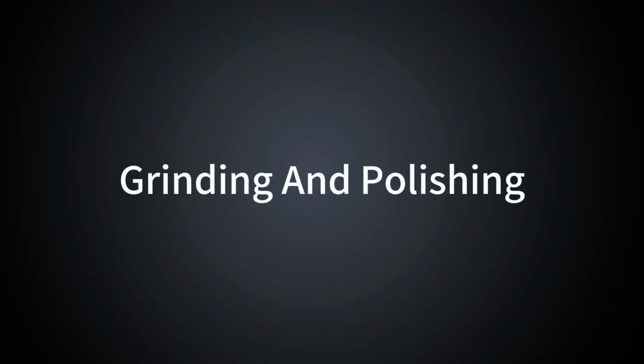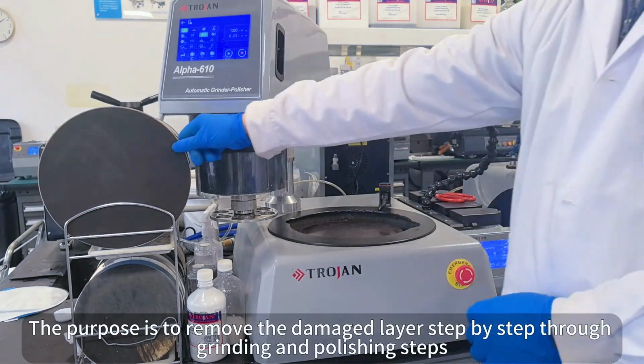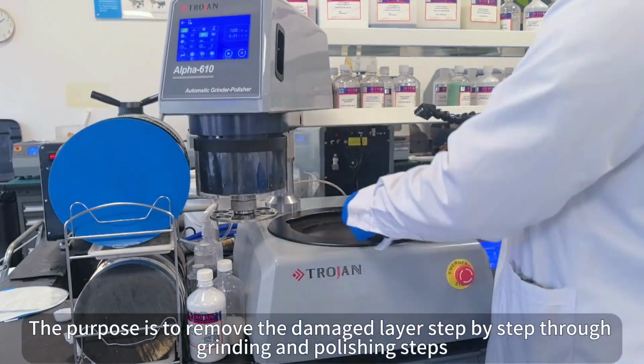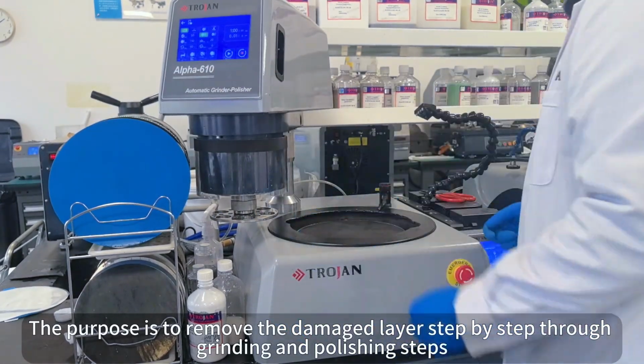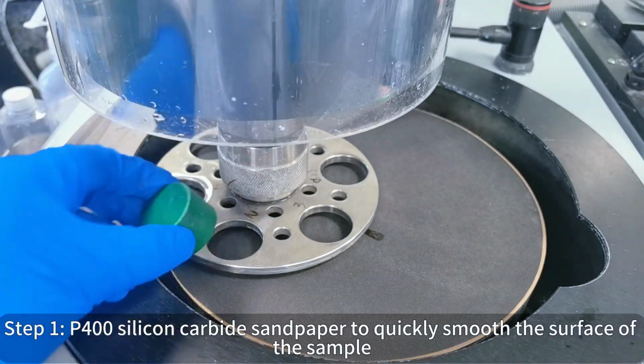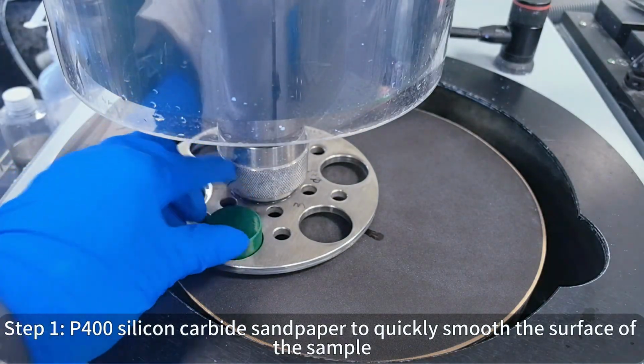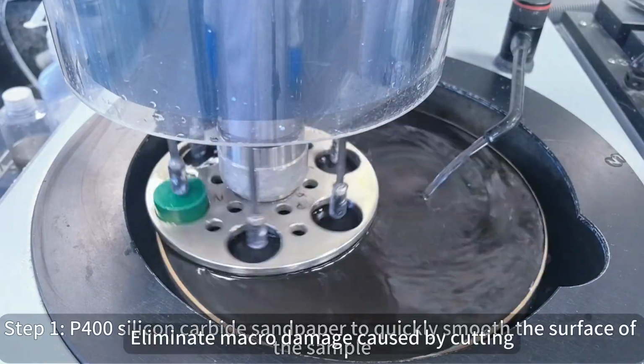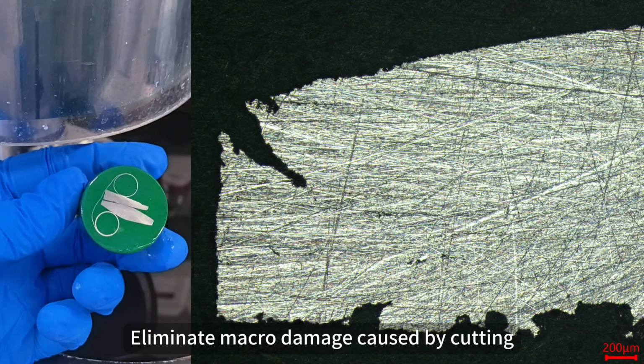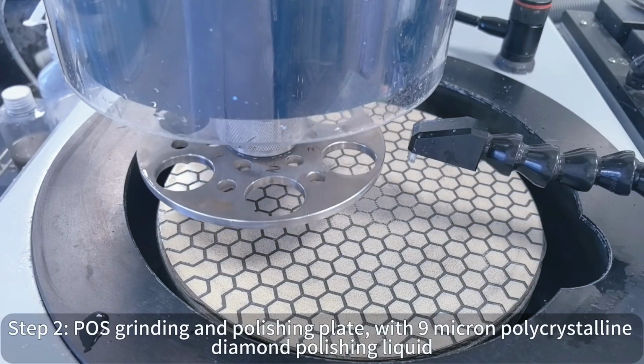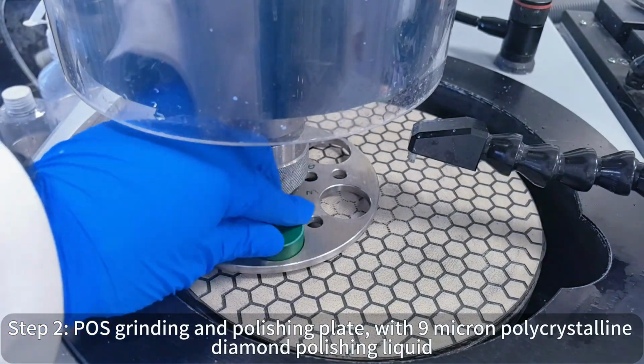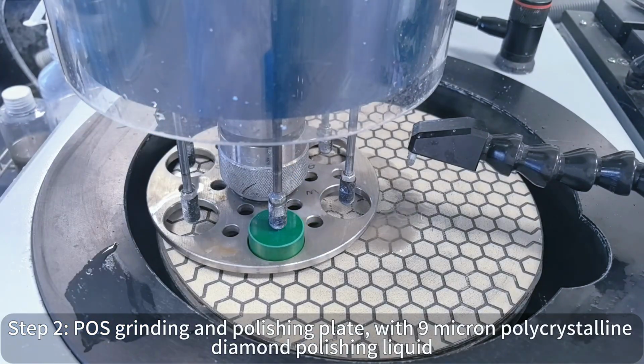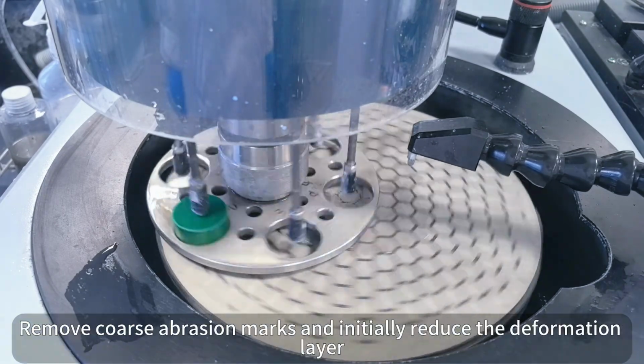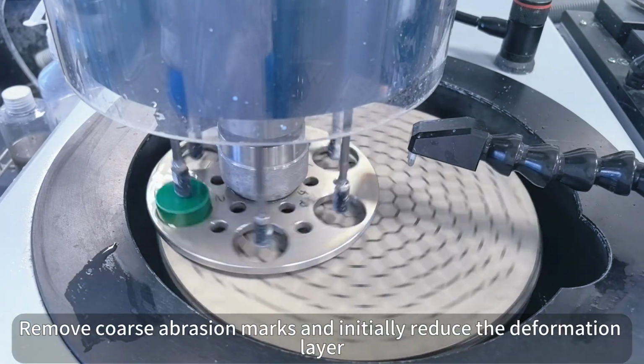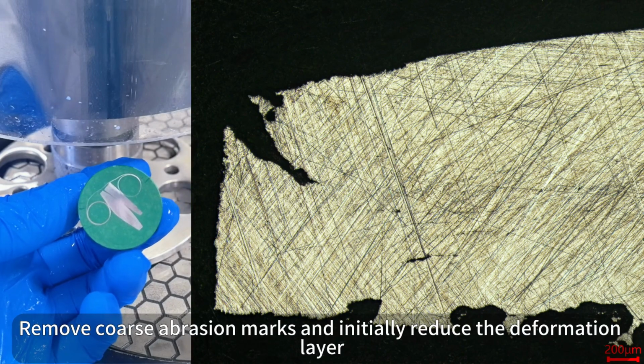Grinding and polishing. The purpose is to remove the damaged layer step by step through grinding and polishing steps. Step 1. P400 silicon carbide sandpaper to quickly smooth the surface of the sample and eliminate macro damage caused by cutting. Step 2. POS grinding and polishing plate with 9-micron polycrystalline diamond polishing liquid, remove coarse abrasion marks and initially reduce the deformation layer.